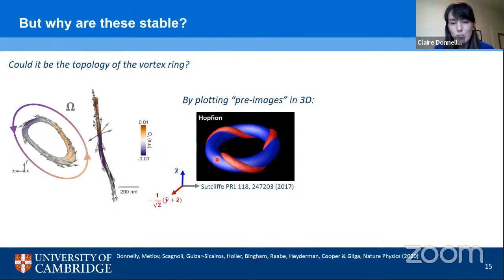Now, what do these tubes mean? We are plotting pre-images here. We have two tubes, a blue one and a red one. Now, the blue isosurface represents a region where the magnetization is pointing in the Z direction. The red isosurface, or the red tube, represents a region where the magnetization is pointing in another direction. And by seeing that these tubes actually interlink a number of times, we see that they have a non-zero Hopf index, and therefore this structure would be a hopfion.